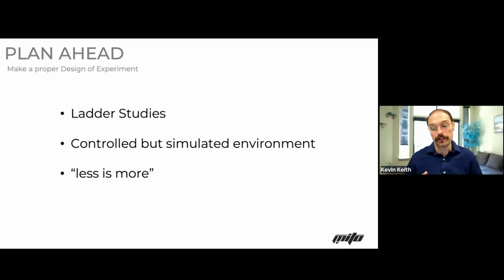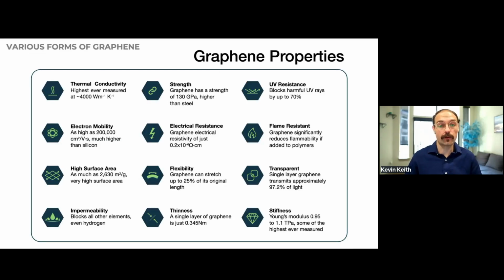And so with these materials, you can always do more with less. You can start getting some really great strength properties depending on the graphene material you plug in, all the way down to 0.05, 0.03, sometimes 0.01% by weight of the resin. So it's legitimately just a sprinkling of this material into the polymer, and it gets the benefits everybody's looking for.